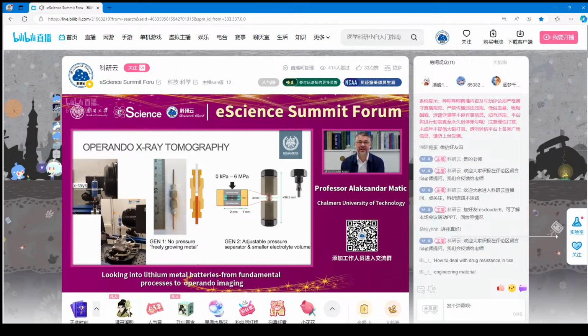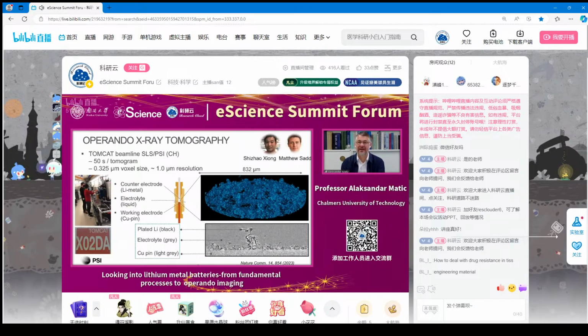And the first experiment we did at the Swiss Light Source. So this was Matthew Sad, who was a PhD student at that time, and then together with Shizao. We were working on understanding this and seeing, can we actually observe the deposition of lithium? And it turns out that with the excellent instruments they have at the Swiss Light Source, we could obtain a full 3D image of this battery within 50 seconds with a roughly 1 micron resolution. And what you see here to the right is actually the morphology of deposited lithium over the whole electrode. And this is how a slice looks.